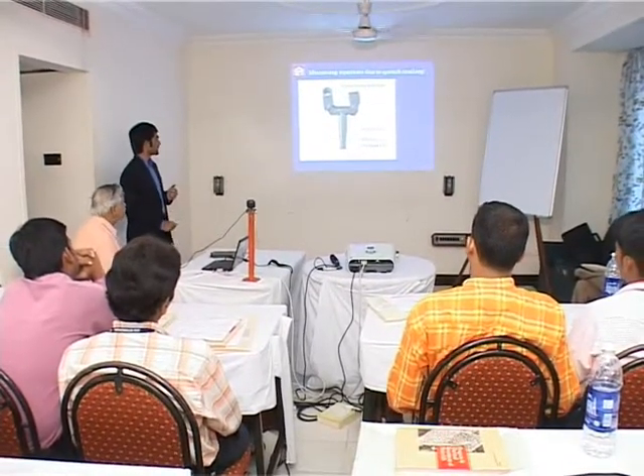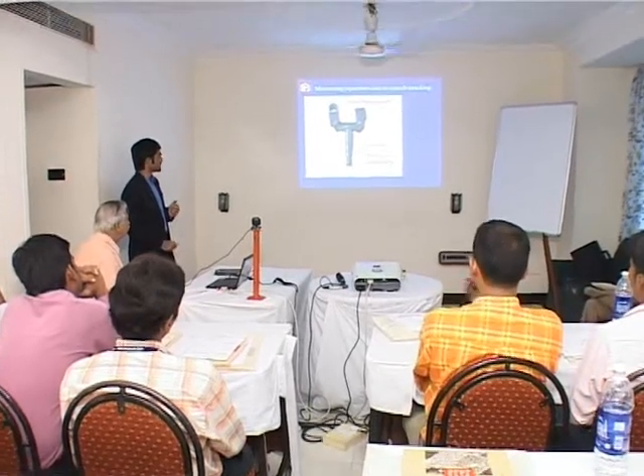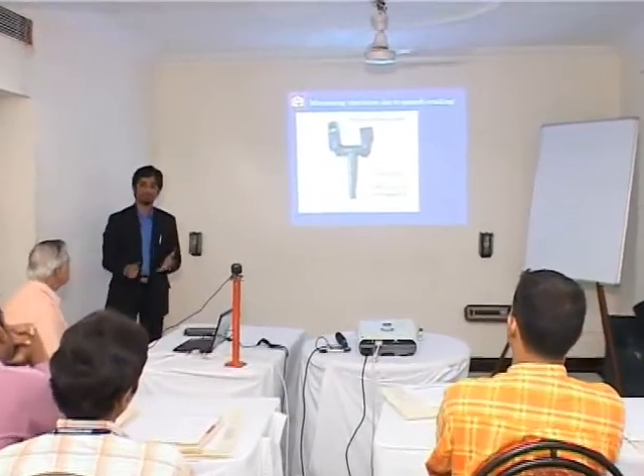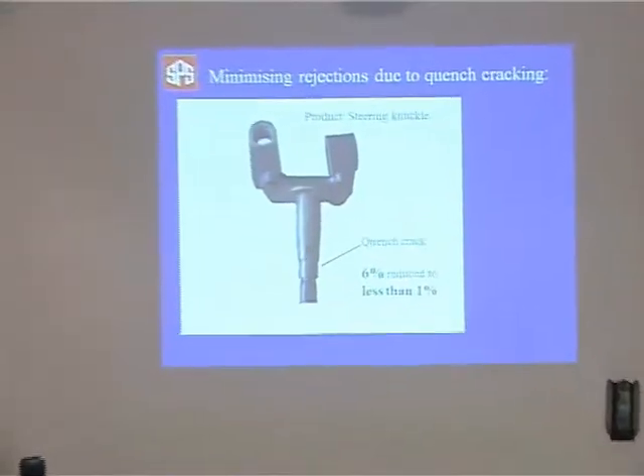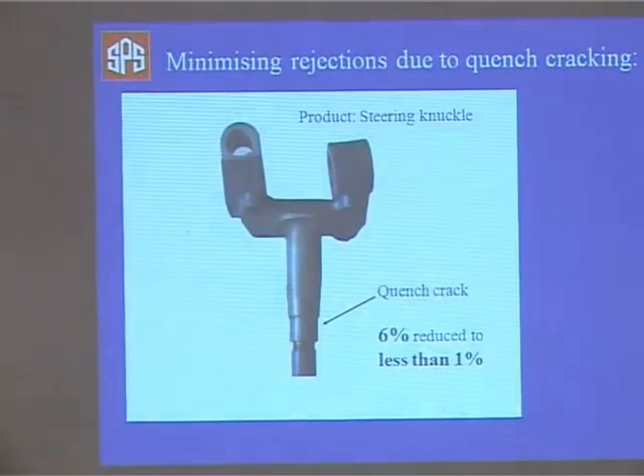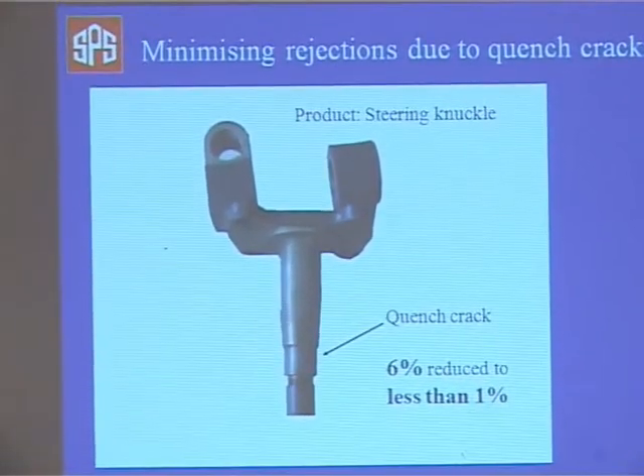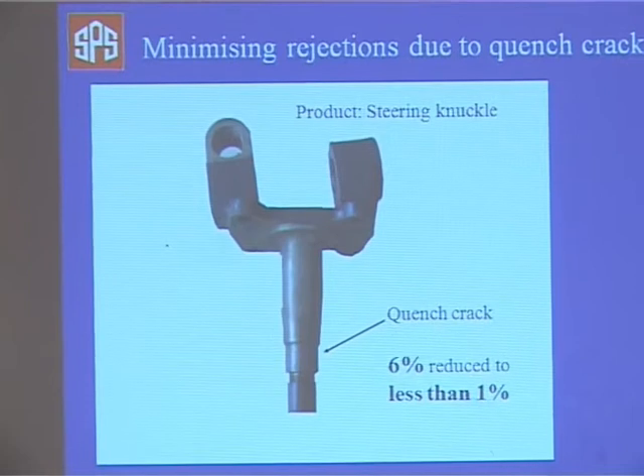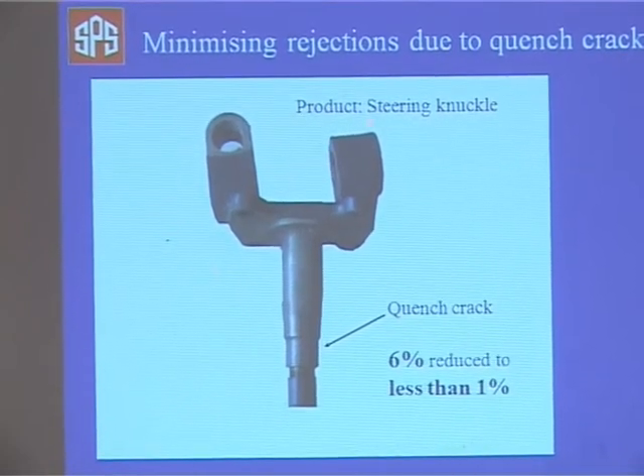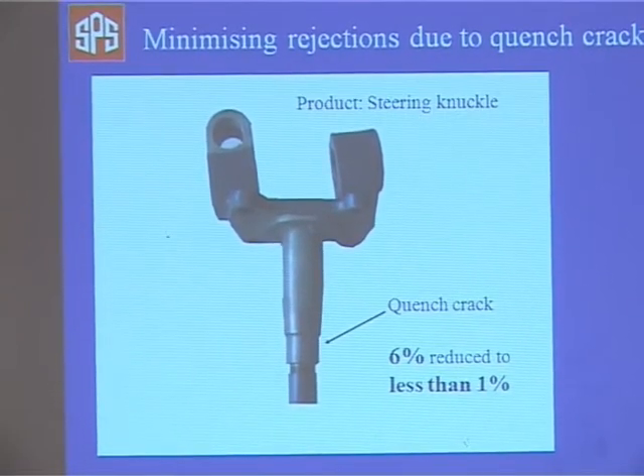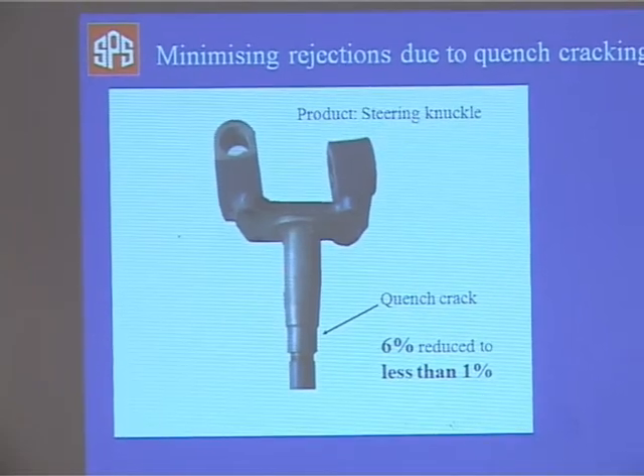Knuckle joint, and our customer would usually have quench cracking in this area, the stem area. And again, when we used an anti-scale compound, the quench cracking was essentially due to scaling. When we used an anti-scale compound, it was reduced to less than 1%, where their overall percentage was 6% in terms of rejections. Imagine 6%, and this is a high volume product, so 6% would be a considerable amount.